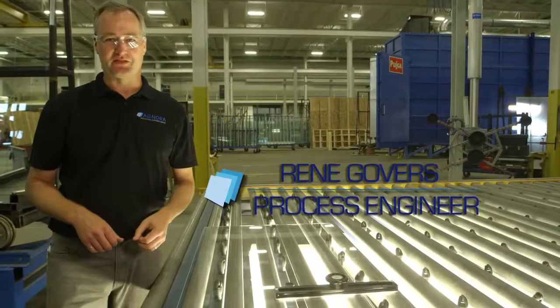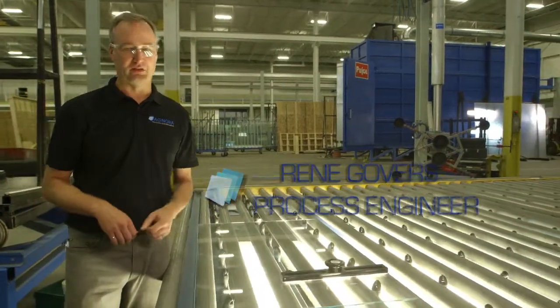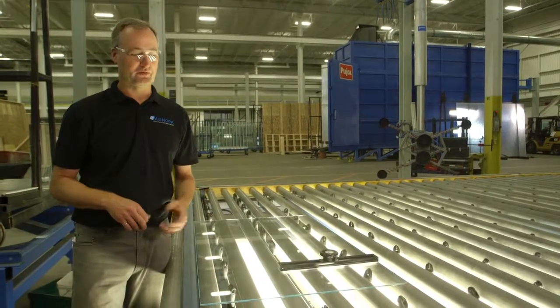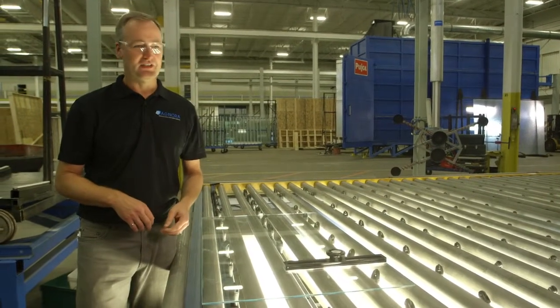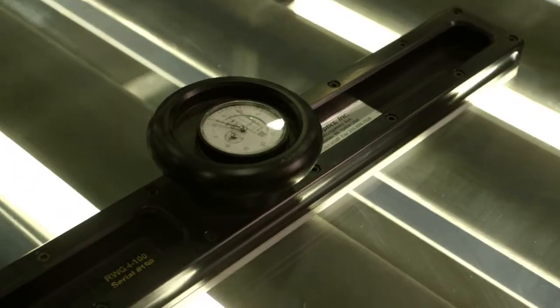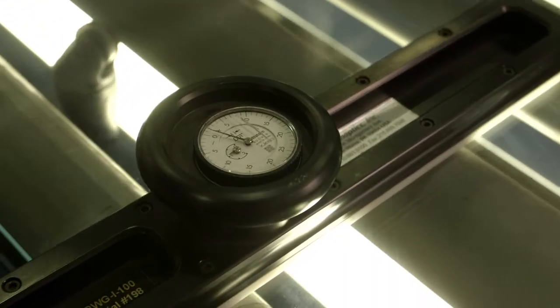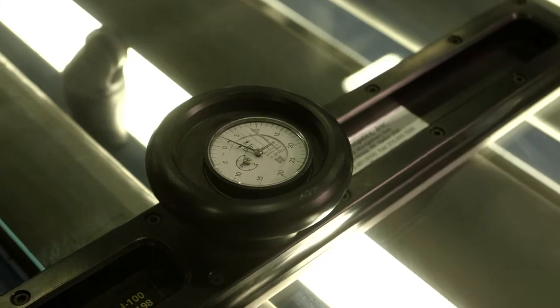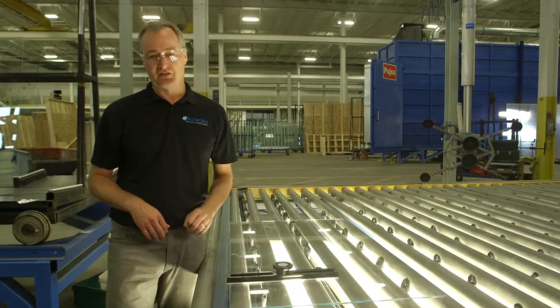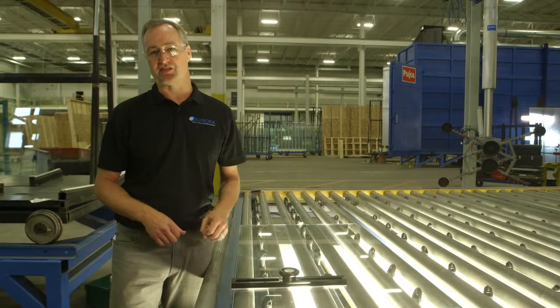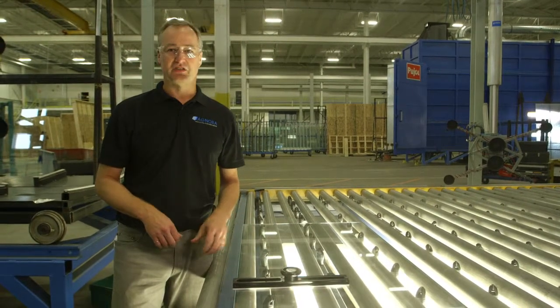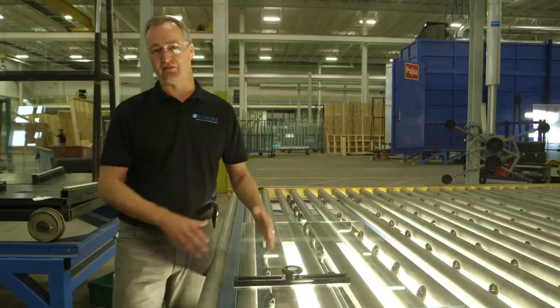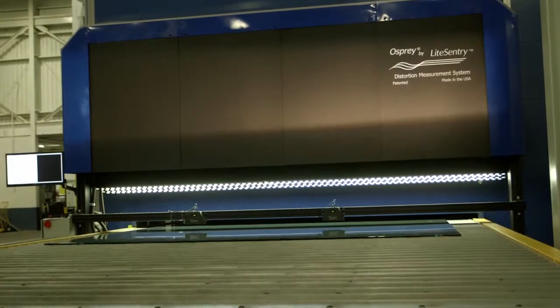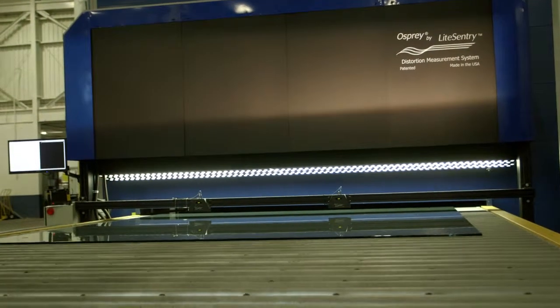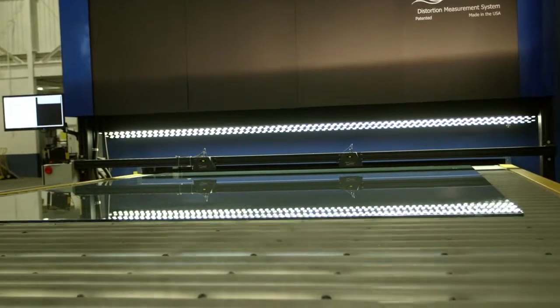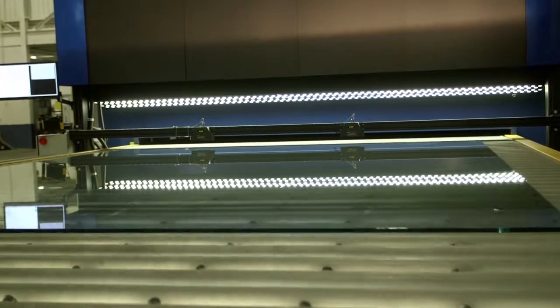One of the other methods of measuring distortion in glass is to measure the roller wave using a flat bar or a 3-point measuring device. Essentially, it is just dragged across the glass, and the physical measurement is weighed of the peaks and valleys within the glass. One of the problems with this is that you cannot measure the outside 6 to 8 inches of the glass doing this. The Osprey by LiteSentry system allows us to get a full measurement across the full width of the glass, giving us complete data, and this is excellent data to use, especially when we have edge curl problems for a laminated product.